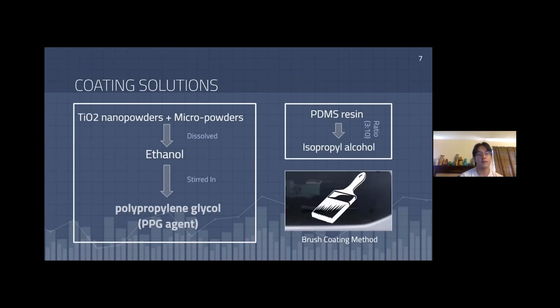And the way to actually make the coating solution, as seen in the diagram here, is that we take the nanopowders and the micropowders of the titanium dioxide and dissolve it in ethanol. And then we're going to stir in a PPG agent. And then we're going to take the PDMS resin and dissolve it in isopropyl alcohol and dilute it for 15 minutes. And then we're going to combine the two solutions by blending them together to make our final coat. And the way we're actually going to apply our coat to the car windshields is through a brush coating method.